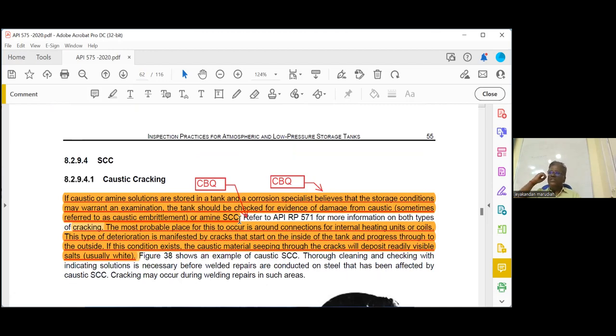If you are storing caustic, you have to expect caustic stress corrosion cracking. Where will it occur? It will be at the internal heating units, because for caustic, we need a temperature of more than 170. And the crack will start inside the tank, and it will be a through crack. There will be a white salt on the cracks. The most probable place for this is around the connection for internal heating units or coils. This type of deterioration is manifested by cracks that start on the inside of the tank and progress through to the outside. If this condition exists, the caustic material seeping through the cracks will deposit readily visible salt, usually white.